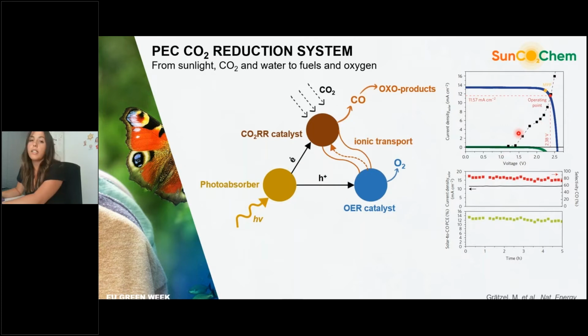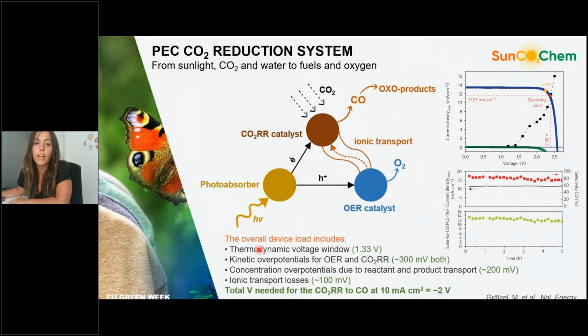In this load curve, there are different components that are included. For instance, we have the thermodynamic voltage window, which is in fact the minimum energy that we need for the reaction to occur. Here is the thermodynamic voltage required for the CO2 reduction reaction to CO. Also, we have voltage losses from the kinetic overpotential for both catalysts, that is determined by how good your catalysts are. And also potential losses determined by the difference in the concentration between the reactants and products, and also the ionic transport losses. Those two losses are mainly generated by the architecture of the device. So if we want to produce carbon monoxide from CO2 at this current density, we at least have to develop a device that will give us a voltage of 2 volts.